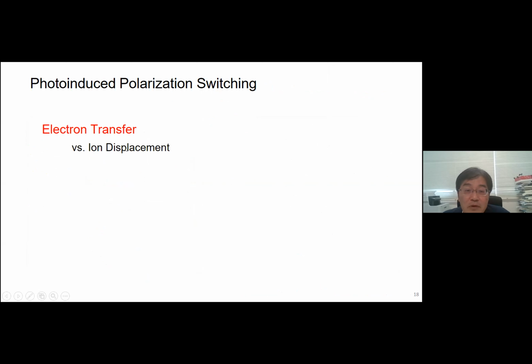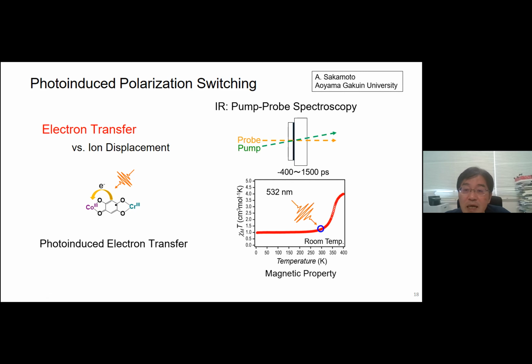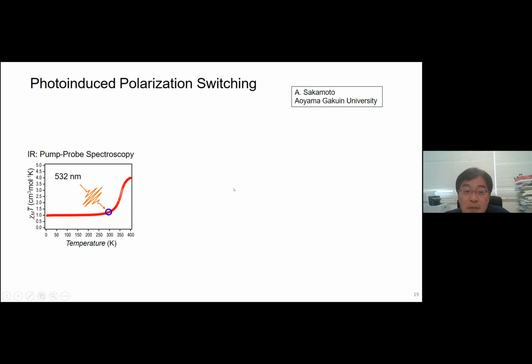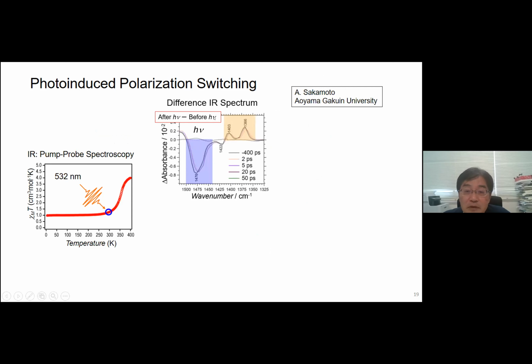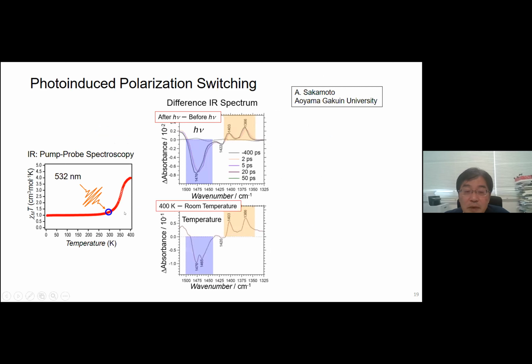And the advantage of electron transfer over ion displacement is that electron transfer can be directly controlled by photoirradiation, as shown here. So this means ultra-fast polarization switching is expected. So we measured a photo-induced effect using IR pump probe spectroscopy at room temperature. And this is a difference IR spectra before and after photoirradiation. And this is a difference IR spectra between high temperature phase and low temperature phase. And this spectra is consistent with this one.